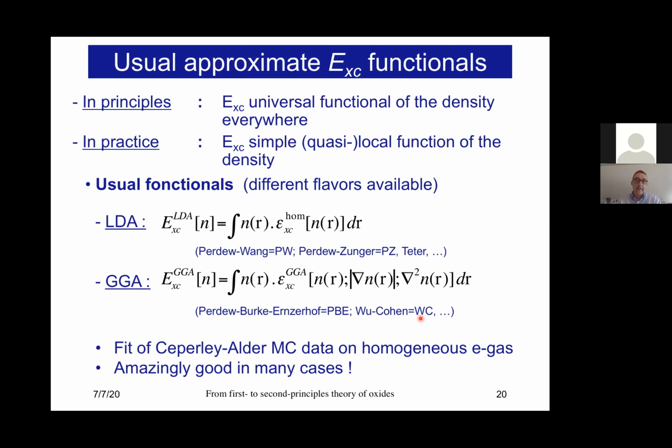But usually we have to choose, and defining the functional we will use will give us some level of approximation. Still, it's not because you move from LDA to GGA that we will necessarily improve the description, because you make an expansion here, you stop somewhere, but when you have an oscillating function, you are not necessarily improving when you go further. And that's something I will show you in a minute. So there is no strict rule to say, okay, this is the best functional. No, we have to try and then figure out what might be the most appropriate for our system.